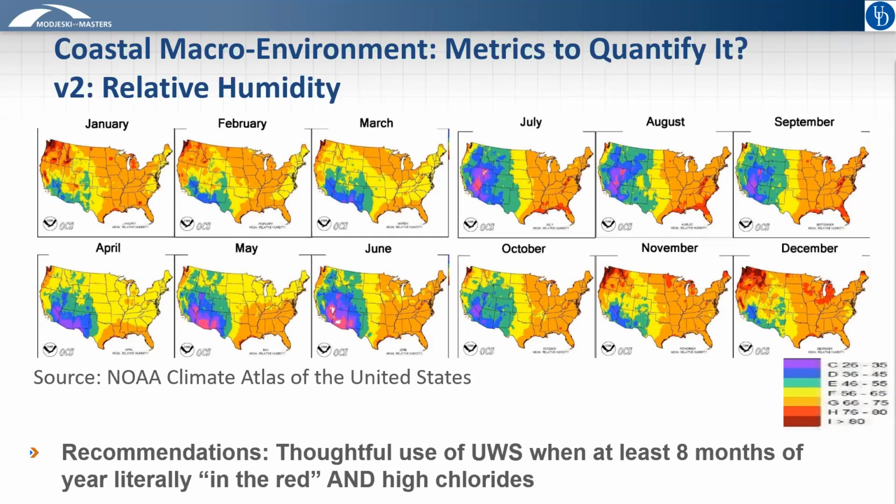From a rough skim of these figures, you can see this generally occurs along a relatively small but important portion along the Gulf coastline. And at these lower humidity levels compared to the time of wetness threshold, significant chlorides are also necessary to be simultaneously present in order to cause accelerated corrosion at levels that may be of concern.